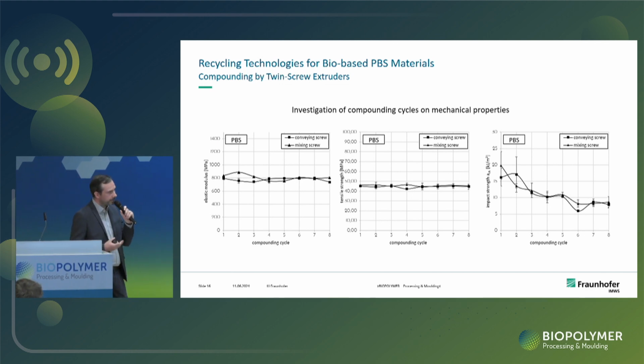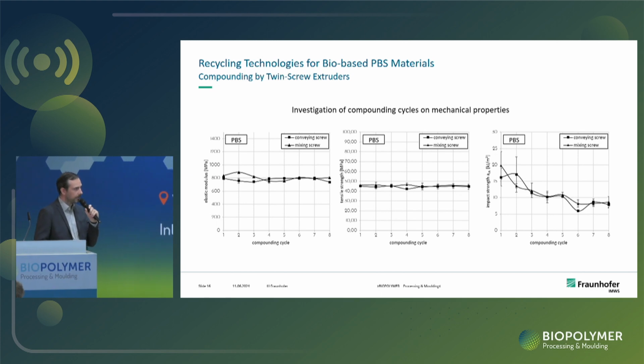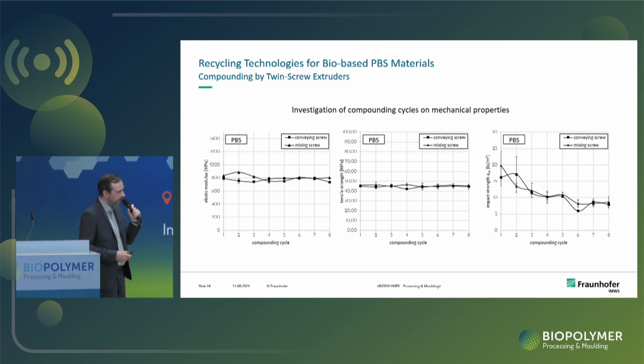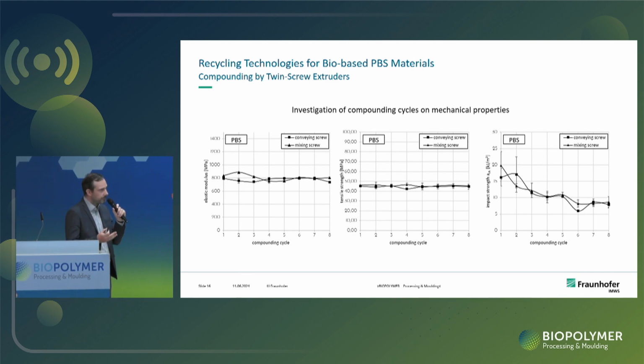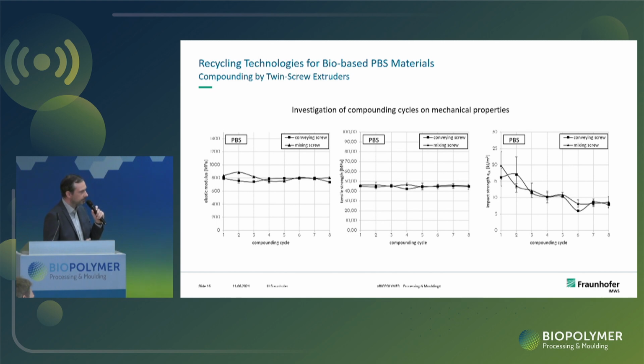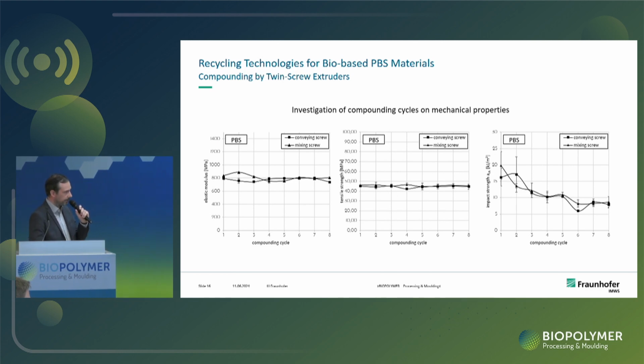So you need modification or fresh material, and this 50% recycling criteria we must fulfill from next year on should be possible also with the PBS, at least for stiffness and strength. We also did not see any influence of the screw design. We investigated 2 different screws, a conventional conveying screw and a certain mixing screw, and there was no significant effect of the screw design on the mechanical properties.